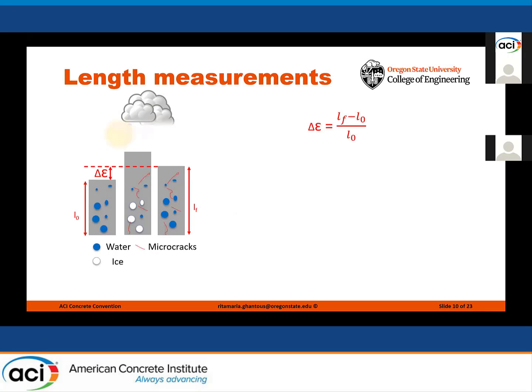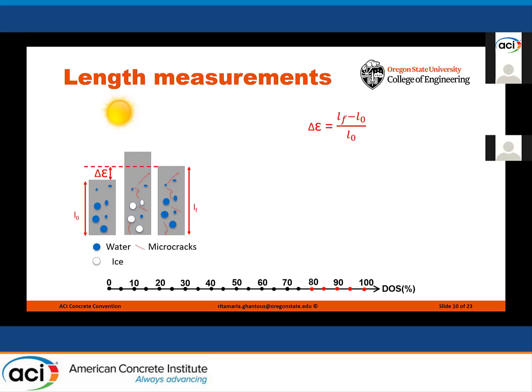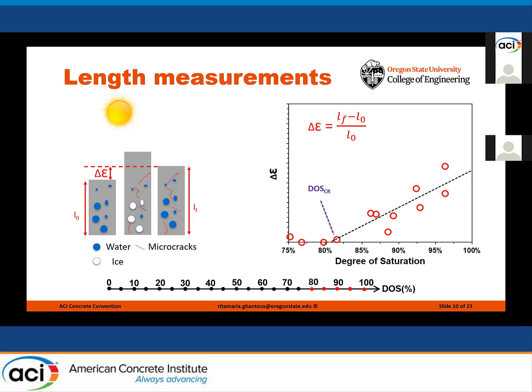Now, when the temperature increases, the ice will melt and the sample will shrink in length again, but will never go back to its initial length. So we'll have a residual strain, written here as delta epsilon, which can be calculated from the difference between the initial and the final length of the sample, as shown in this equation. This residual strain has been proven to be a good indicator for freezing and thawing damage.